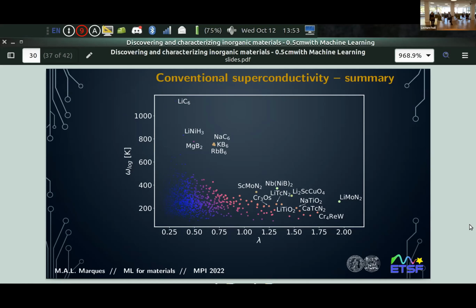It is if you do two-gap superconductivity. If you take the isotropic average, it's much smaller. It's half, 17 Kelvin or something like that. So this is just isotropic superconductivity. But as magnesium diboride is the only compound that we know where two-band superconductivity doubles TC, we're probably okay for most compounds, right? But you're absolutely right.